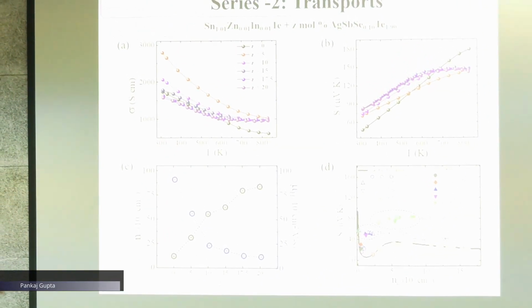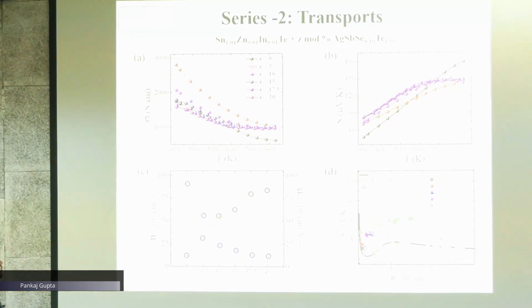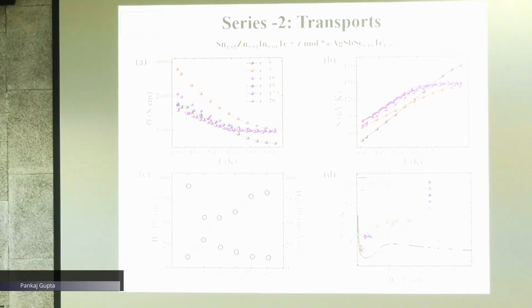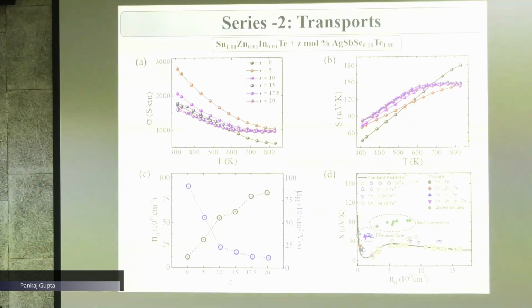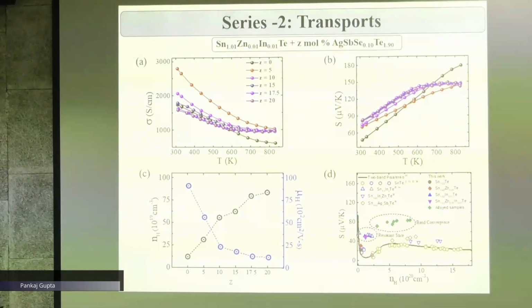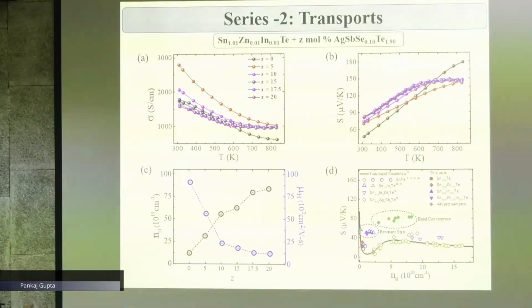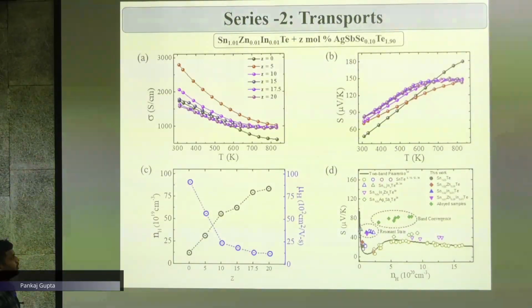So here we can see that this z equal to 0 is the optimized sample from our previous series, and after alloying, initially we are getting higher electrical conductivity because of the increased carrier concentration. More alloying is reducing the electrical conductivity because the mobility is going to decrease a lot because of disorderness. And you can see the Seebeck is increasing a lot because the density of states effective mass is very high.